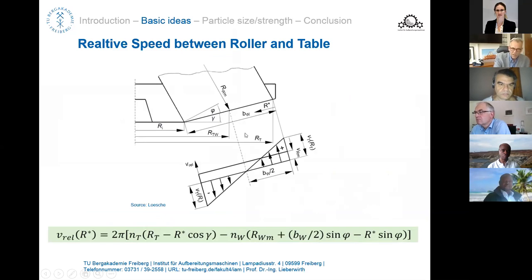In the VRM, you have differential speed underneath the roller. So you have the rotating table, not shown here, and you have your roller here, section shown here. In the contact area between the roller and the rotating table, we have a speed pattern like this one. So if you have adjusted the speed of the roller in the center to the speed of the table, so that you have a zero relative speed between the two at this point, then on the outer side, due to the increased diameter of the conical roller, you have a higher speed of the roller compared to the table, while on the inner side, with the lower diameter of the roller, you have a lower speed.